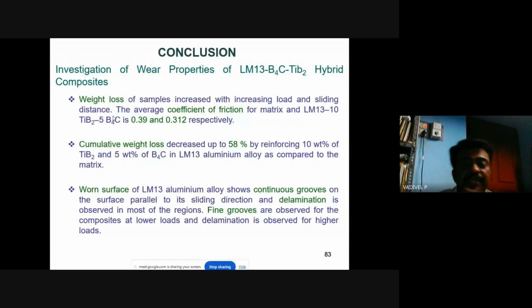And the next one is the weight loss. The weight loss of the samples increased with the increasing load and the sliding distance. The average coefficient of friction for the LM13 matrix and for 10 weight percentage TiB2 and 5 weight percentage boron carbide is 0.39 and 0.312 respectively. The cumulative weight loss is decreased up to 58 percentage with the reinforcement of 10 weight percentage and 5 weight percentage. The worn surface has continuous grooves along the sliding direction, and delamination is observed in most of the regions. Fine grooves are observed for composites at the lower loads, and delamination at the higher loads.